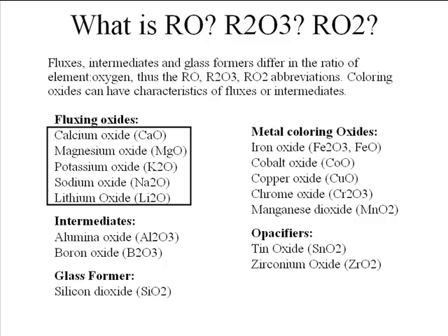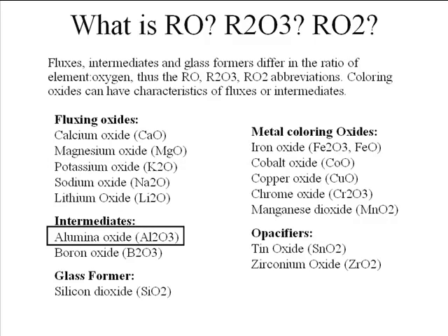To give the melted glaze some body so it doesn't run off the ware, and to give the fired glaze more strength, hardness, and leach resistance, we need this, alumina. But put too much of this and the glaze fires matte. What's this? It is boron. It's magic. It is both a flux and a glass former, and it comes in frits. Most of the traditional ceramics industry is built on this wonderful oxide. Only high-temperature glazes do not need it.